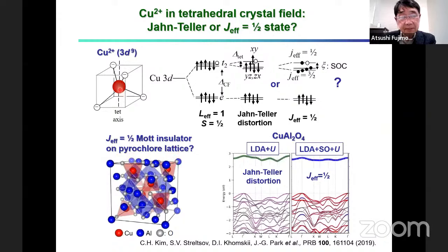This is copper 2 plus, coordinated by a tetrahedron of oxygen. And this is an interesting system because if our system remains perfectly tetrahedral, then the spin orbit interaction splits the T2 into J effective 1/2 and J effective 3/2, and one hole occupies here. So the system becomes a so-called J effective 1/2 system.